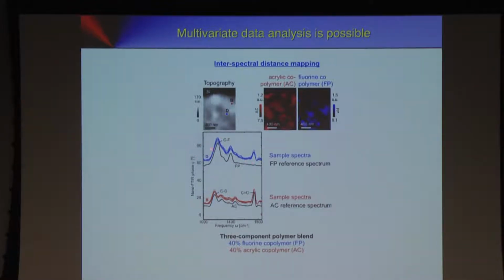And here you see different spectra. Each spectrum is from 1 pixel, and these are 6 or 9 neighboring pixels here. So you see already that the spectra are pretty reproducible and stable here. So now we calculate the spectral distance between the reference spectrum and the spectrum at each pixel, and then we get these red and blue maps here. And this red color indicates once a spectrum is very similar to this reference spectrum here. And so we can get a map that indicates to us the distribution of the acrylic copolymer, and here the fluorinated copolymer. And we see that they are at different locations.